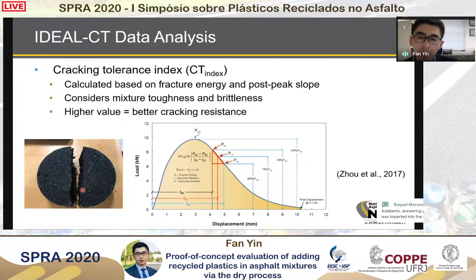When we do the TSR, we only look at the peak number. But in this case, we look at the entire load versus displacement data, and we consider the fracture energy and the post-peak slope. By considering all these parameters, we calculate the final cracking index parameter called the CT index. A higher number indicates better cracking resistance at intermediate temperature.